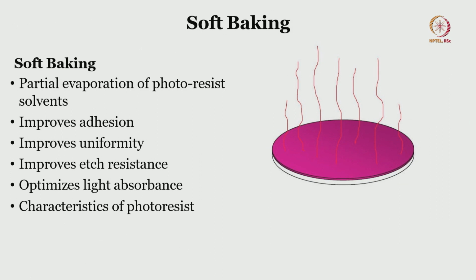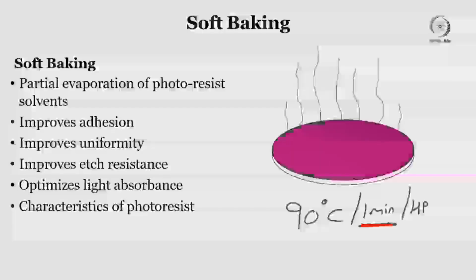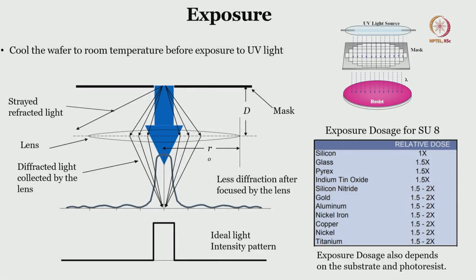Soft baking, like I said, photoresist comes with a data sheet, but if you go for positive or negative photoresist, it is 90 degrees centigrade for 1 minute on a hot plate. So, this is the soft baking temperature and time on a hot plate, but if it is an oven, then the time would differ if you load the wafer in the oven after spin coating the photoresist. What does soft bake do to the photoresist? So, partial evaporation of photoresist solvents improves adhesion, improves uniformity, improves etch resistance, and optimizes light absorption or absorbance characteristics. These are the characteristics of the photoresist.